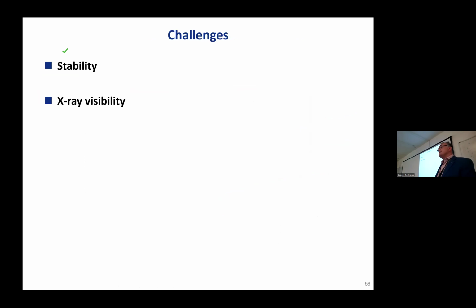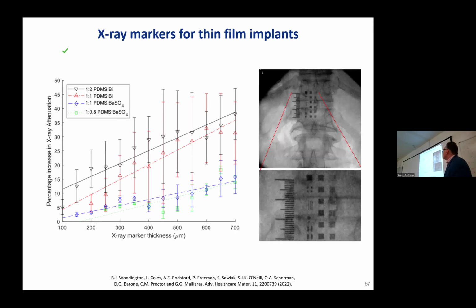Another challenge is X-ray visibility. As you make this device very small, you put them inside the body and then you cannot see them anymore. They don't have enough material to scatter X-rays. And we ran into trouble with that when we put the first implants in. We couldn't see them. It took us a year to develop X-ray markers that are compatible with microfabrication that we can now integrate to the implants to be able to see them with fluoroscopy.